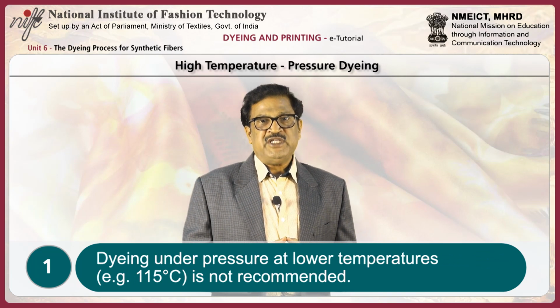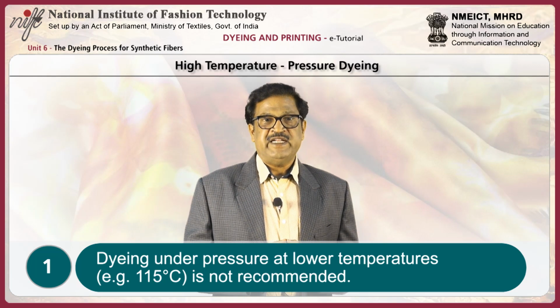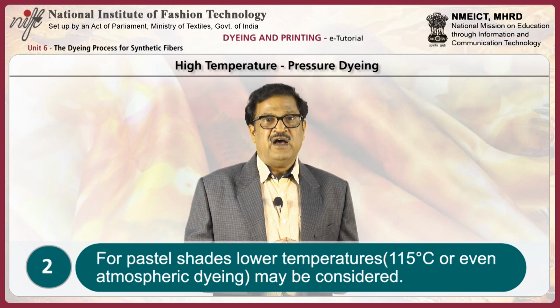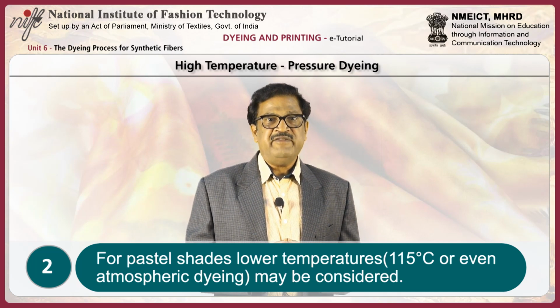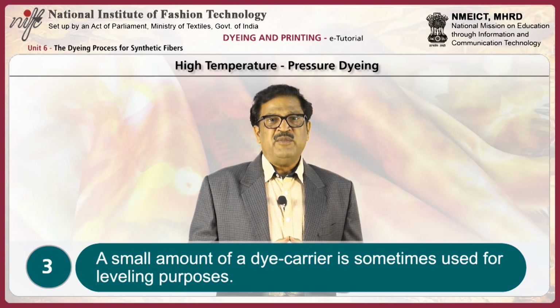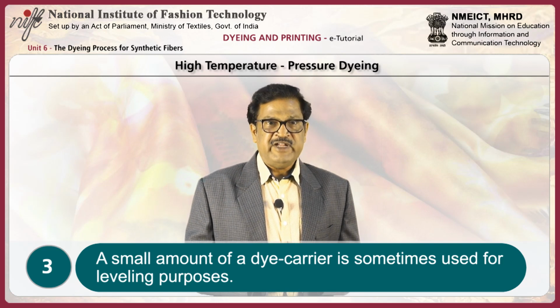Dyeing under pressure at lower temperatures around 115 degrees centigrade is not recommended. However, for pastel shades, lower temperatures around 115 degrees centigrade or even atmospheric dyeing may be considered. A small amount of a dye carrier is sometimes used for leveling purposes.